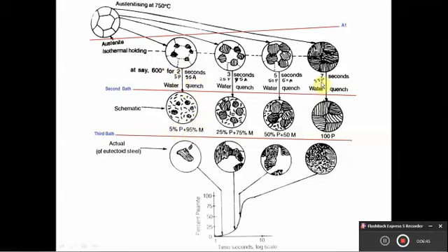Similarly here, almost 99% pearlitic transformation has occurred, so it will show 100% pearlitic structure. So metallographically you have to find out the percentage of pearlite transformed. Here graphically it is shown as a transformed pearlite versus time curve. So this will be the incubation period. As the time increases, from 2 second to 5 second and 7 second, the percentage of pearlite transformation will increase. After joining these points we will get an S-shaped curve.